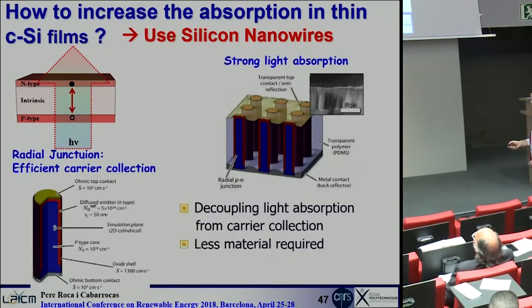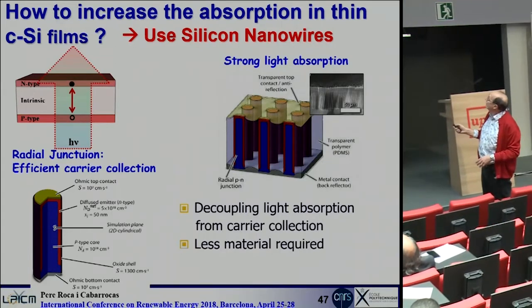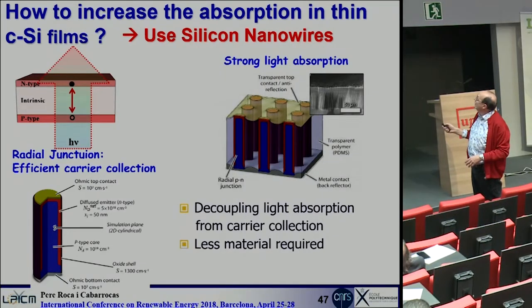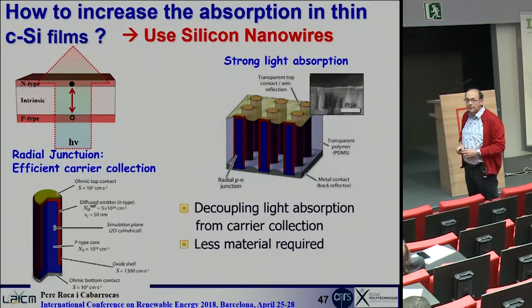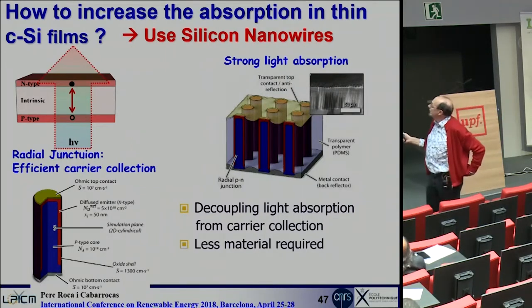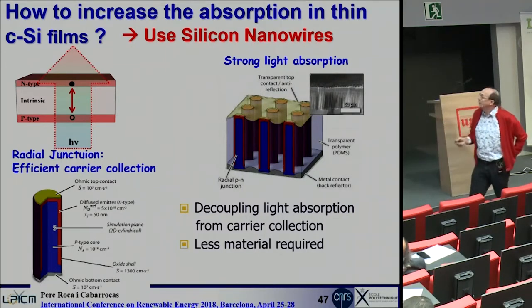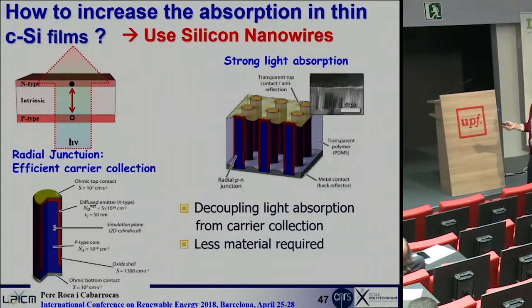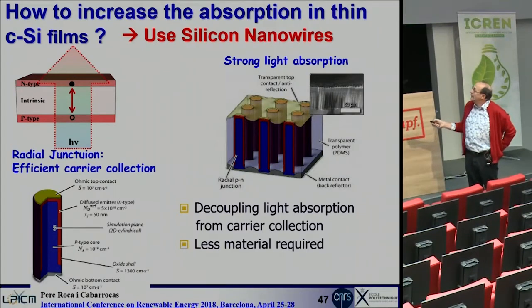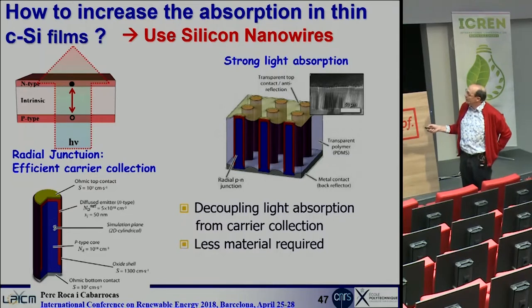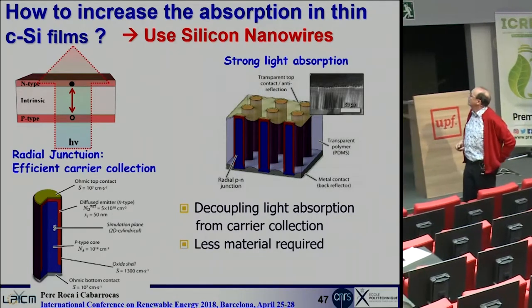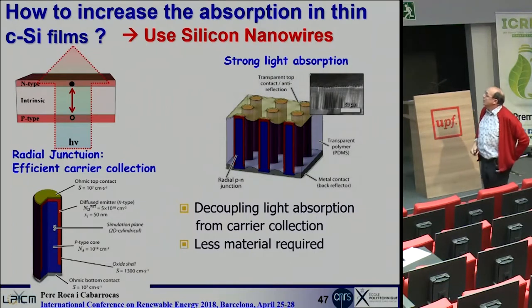So if I use a silicon nanowire, I put the p-type in the core and the n-type around it. This is a radial junction, so I can decouple light absorption and carrier collection. And by doing that, I can use less material to have a strong light absorption and still keep a good carrier collection. How do you make the nanowire solar cells?